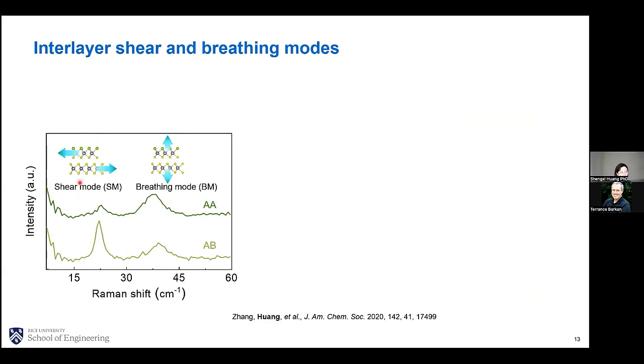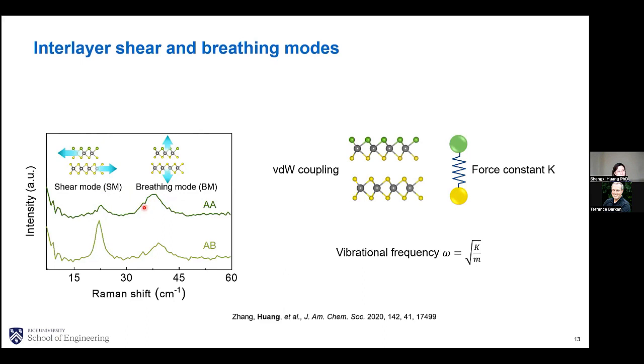In these interlayer Raman modes, the entire layer of the 2D material will vibrate as a whole unit compared to the adjacent layers. So we have interlayer shear modes corresponding to this one and interlayer breathing mode corresponding to this one. We can understand these interlayer Raman modes using a linear chain model. In a linear chain model, we can consider the 2 layers of 2D materials as 2 small balls connected by a spring with a force constant K.